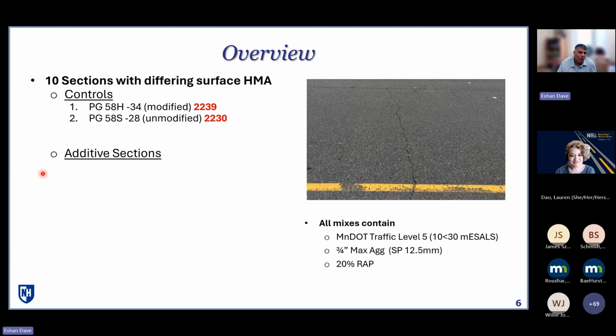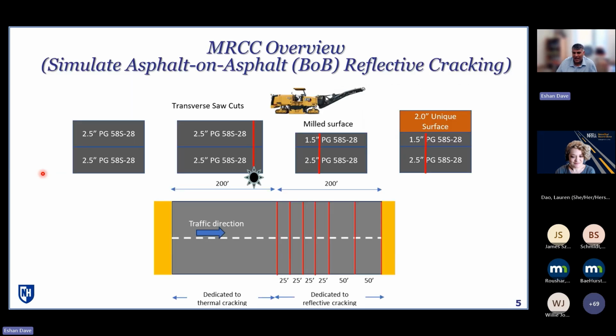Here it was done more out of necessity to create that really severe condition underneath. Now they did do some air blowing after cutting these and really brooming to make sure that there was no debris stuck inside these sockets, so that you didn't end up with incompressible particles in there. But again, the idea was to create the most severe condition where your underlying pavement has like a full depth cut or crack in it. Personally, my opinion would be to not do that.